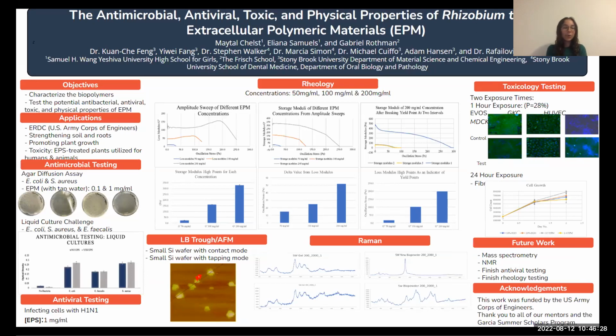To test the polymer for potential antimicrobial properties, we performed an agar diffusion assay with E. coli and S. aureus to test on both gram-positive and gram-negative bacteria. For our first test, we used Petri dish testing with tap water and incubated overnight. We didn't observe a zone of inhibition, indicating bacterial growth and a lack of antimicrobial properties.